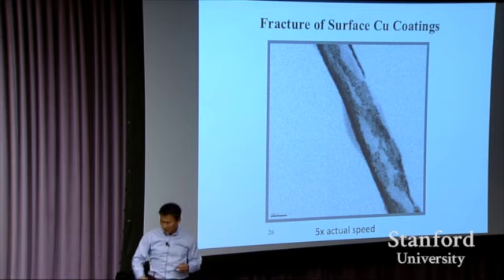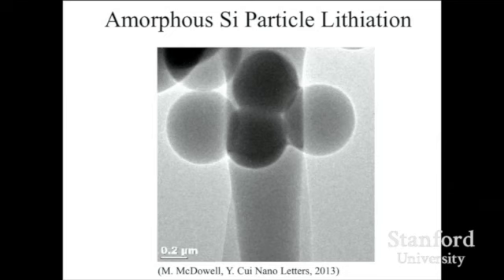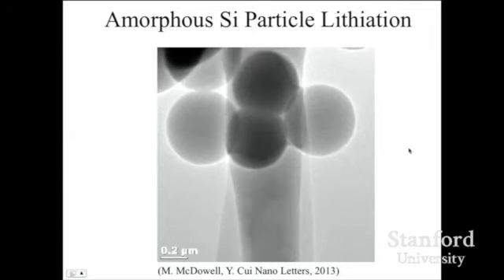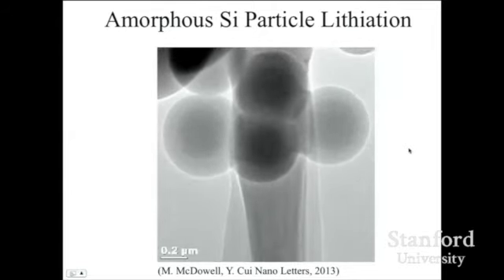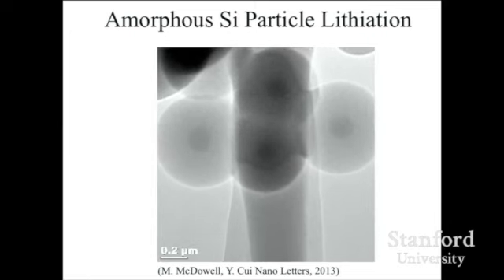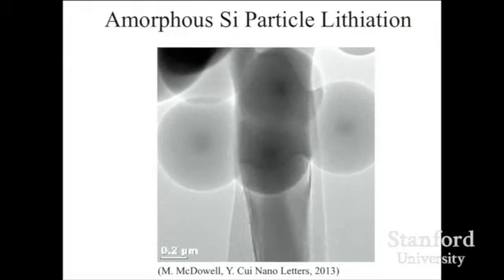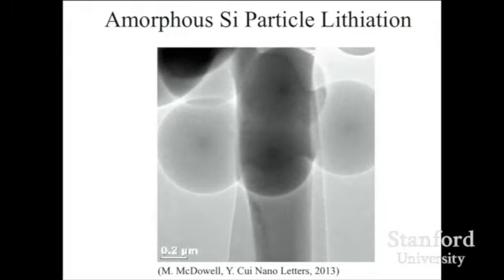They're small enough. And this is another structure using an amorphous silicon particle. It turned out that not only crystalline silicon can store lithium, amorphous can store lithium as well. If you look at how lithium comes into amorphous silicon, this is an amorphous particle. You see this amorphous silicon particle get lithiated, and there's a phase boundary right there. Using this type of tool, we started to understand what's happening in these battery materials. This is very, very cool.